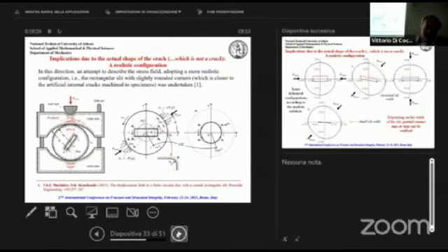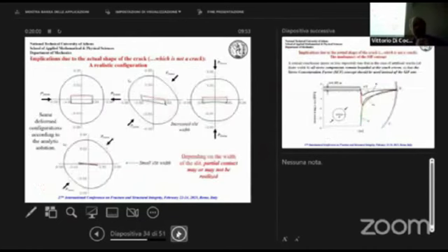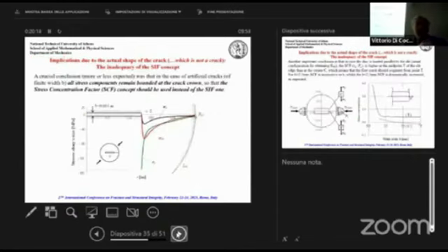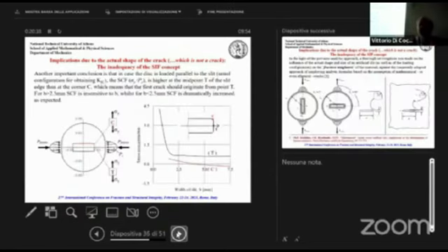we ignored the actual distribution, and we found some interesting results concerning the distribution of the displacement field, which could lead to lips in contact, depending on the initial width of the notch. What was more important, however, is that all stress components remain bounded. There is not a singular field, which means that perhaps the stress intensity factor is not the proper one when we deal with problems in practice where the crack is by no means a mathematical singular crack.